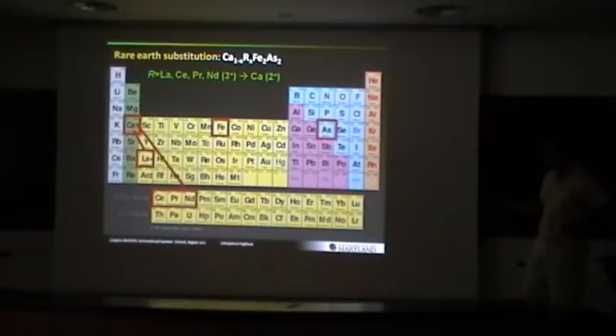In any case, you have to be very careful about doing experiments under pressure in a system like this. So we decided to do rare earth substitution to see if we can induce this collapse at ambient pressure conditions, so we can do all these experiments without this problem. So we basically take the light rare earths, which are a good size match for calcium, and try to put them in.